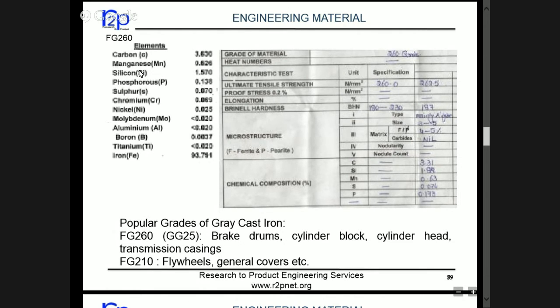So carbon is higher and silicon is higher, right? And another aspect is hardness. Hardness in FG260 allowable as per IS is maybe 180 to 230. But if we have hardness above 210, then machinability becomes an issue, right? So we try to stick to the lower hardness range allowed in this grade, maybe 185, 195. Above 195, productivity will go down and your tool wear will be more. So we have to restrict the hardness to these ranges.